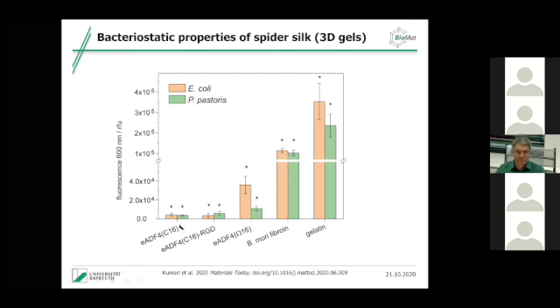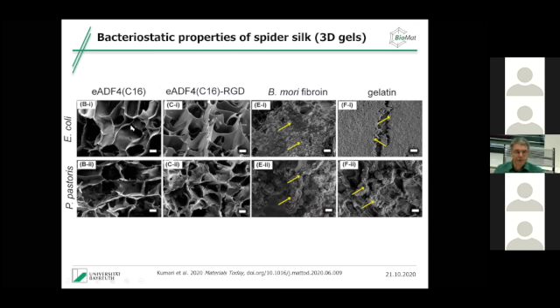And even if we modify this silk here, if we remove the charges completely, kappa16 is uncharged silk, then you see that we lose some of the ability of repellency. But be aware, here's a break in the y-axis. So this is orders of magnitude higher in silkworm silk and in gelatin. And this is how it looks. So what we did, we floated these hydrogels with bacteria and yeast. We incubated that for days. And then we just washed it. And you see that both spider silk hydrogels are absolutely clear. There's no single bacterium in there. And the silkworm hydrogel and the gelatin hydrogel are actually overgrown with the bacteria and with the yeast.